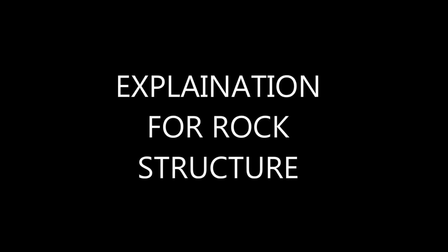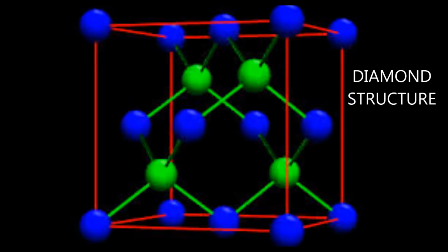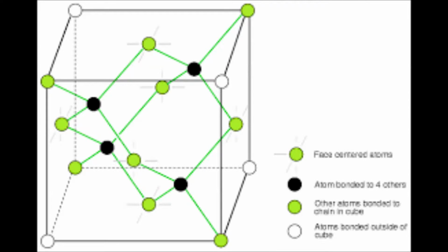The rock is made of silicon elements arranged to form a diamond structure. The space lattice of diamond is face-centered cubic. The primitive basis of the diamond structure has two identical atoms at coordinates 0, 0, 0 and 1/4, 1/4, 1/4 associated with each point of the FCC lattice. Because the conventional unit cube of the FCC lattice contains 4 lattice points, the conventional unit cube of the diamond structure contains 8 atoms. There is no way to choose a primitive cell such that the basis of the diamond contains only one atom.